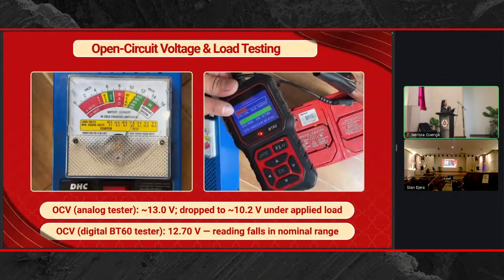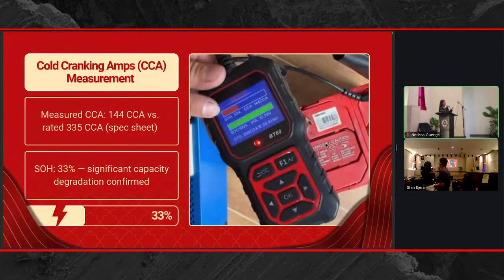So for the open circuit voltage and load testing, the OCV on the analog tester shows a 13 volts measurement and drops to 10.2 volts under applied load. And sa digital BT60 tester naman po natin, 12.70 volts, which is yung reading natin falls in the nominal range. So the cold cranking amps naman na measurement, it shows na 144 cold cranking amps, which is kung kukumpara natin sa specification sheet, dapat po ay 335 CCA siya. And ang state of health na pinakita po sa testing natin ay 33%. So significant capacity degradation confirmed.